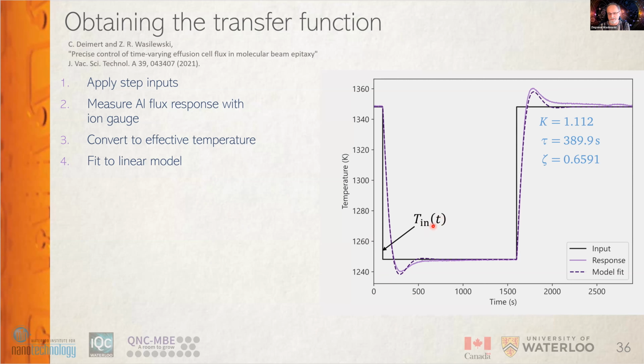First, you have to understand all the dynamics of the cell. So you give it a very rapid ramping, which is dropping the temperature as fast as you can. You're dialing a much lower temperature than steady, and then the same up. And that generates the dependence of the atomic flux, which is plotted here, in this scale of effective temperature, not flux, but I'm not going to go into details of that. So this is basically how the melt is responding.